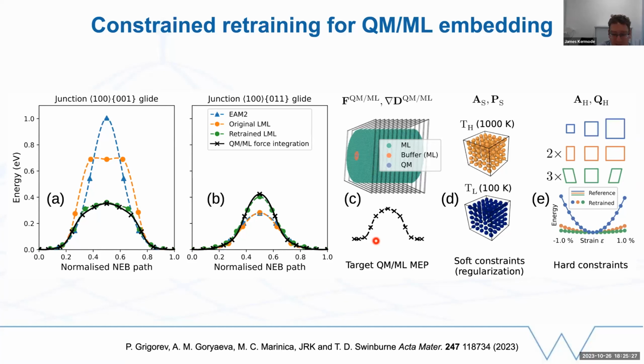We had the glide barrier for the dislocation that was measured using the fully quantum mechanical slash machine learning approach, so the multiscale coupled approach with the short 2D dislocation simulations. We wanted to make sure we still had good behavior on the molecular dynamics. So we put in some configurations that ensured that we essentially regularized the constrained refitting. So we put in some high temperature and some low temperature bulk MD configurations.